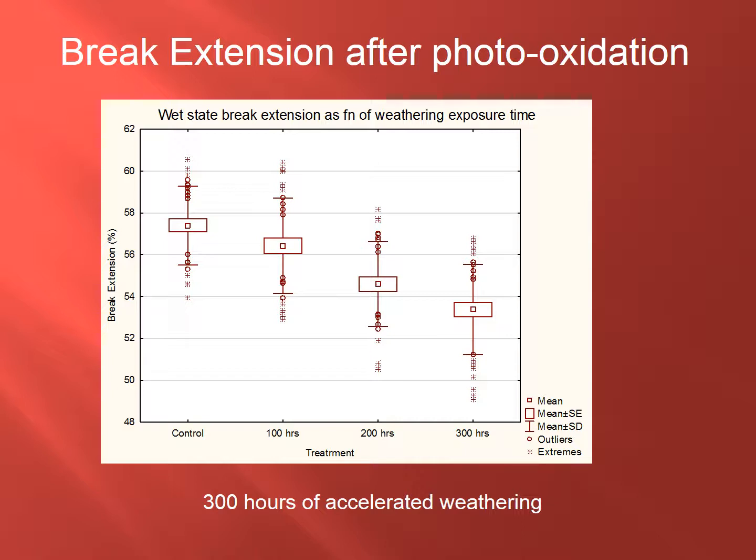It's well known that sun exposure can compromise the hair protein structure and diminish tensile properties, with the mechanism generally being ascribed to photochemical oxidation. Therefore, I think we've traditionally assumed that chemical oxidation and photochemical oxidation likely impact hair structure in a similar manner, the only difference being the source of the oxidating stimulus. But consideration of break extension results shows polar opposites in the response to these two insults and must indicate that the internal structure has been impacted differently.